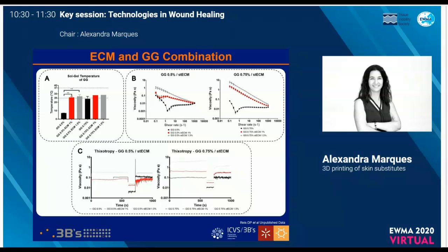We could also see that they have this shear thinning behavior, so the viscosity diminishes with increasing stress, except for this material that is just our control, the gellan gum, with different, very low percentages of polymer. And importantly, we did a test that shows that after printing, the material recovers its properties, so it allows us to take advantage of the characteristics that it presents.